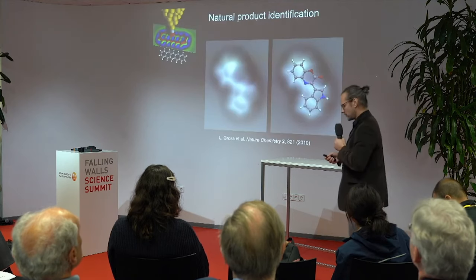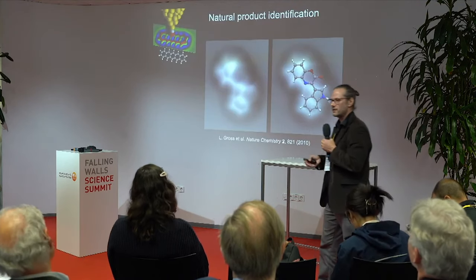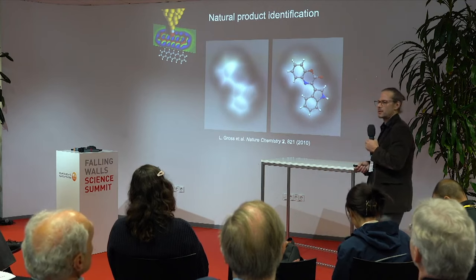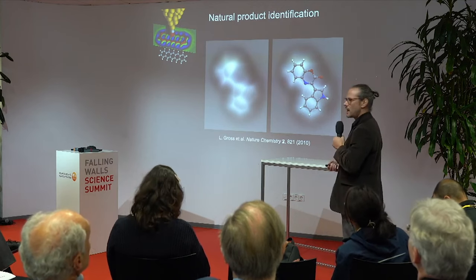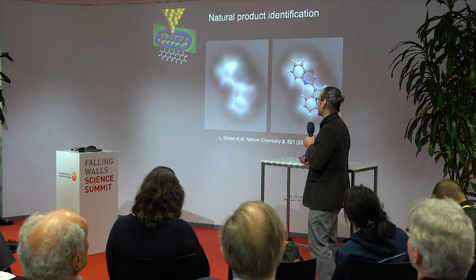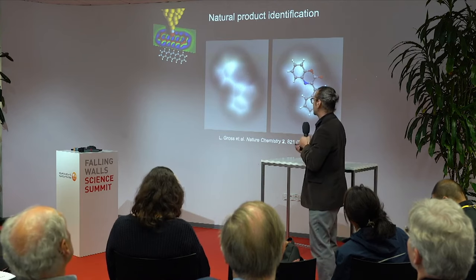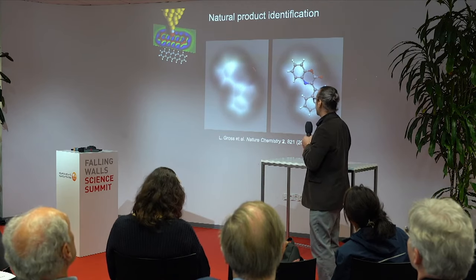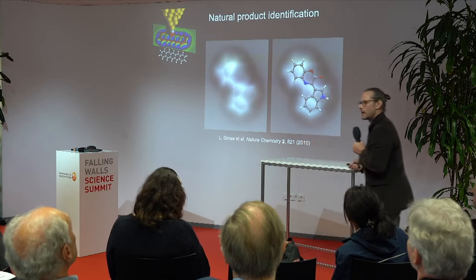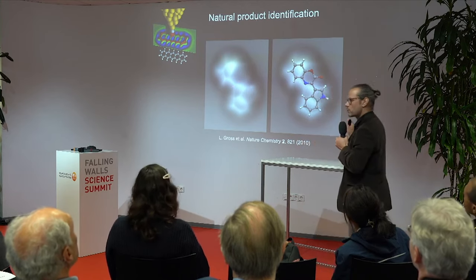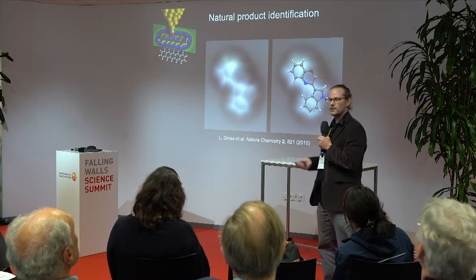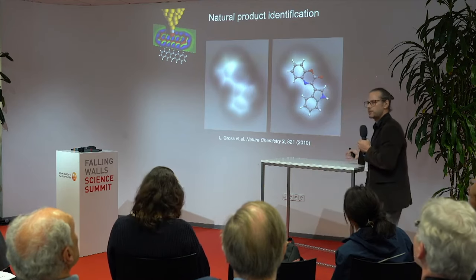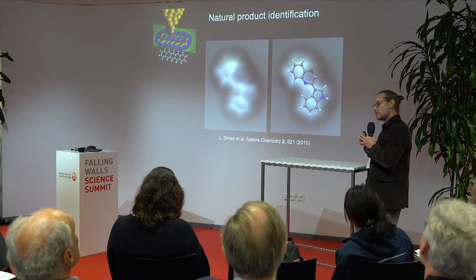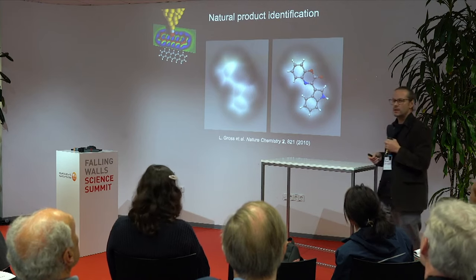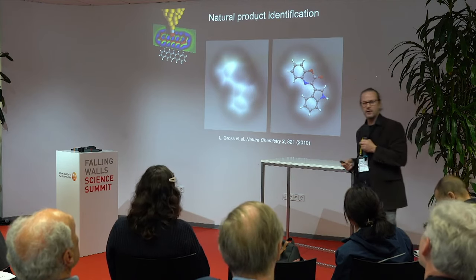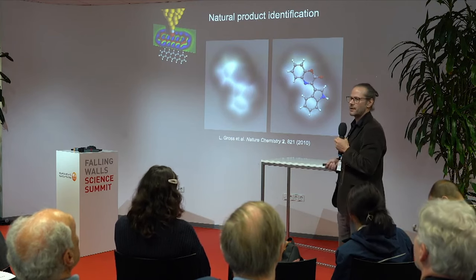And now, what is it good for? Of course, there is a very direct application, and that is identifying molecules. So this is a metabolite hauled up from a submarine from the Mariana Trench, and it was difficult to assign this molecule, and by taking images, we could actually help resolve it. And this is important to look at these metabolites for new cures and medicines, but this is a niche application of our technique. Usually, if you have all the same molecules, then nuclear magnetic resonance and mass spectrometry are the gold standards, and usually you get the structure.